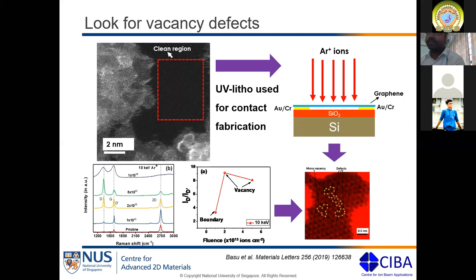So now what we can do in SIBA, as I told, we do ion beam related research as well. The idea is to create openings in graphene, right? We can use a broad beam exposure to expose graphene, because the ion beam, particularly a low energy ion beam, can create vacancy defects. Then you can see some defects created in the graphene. In general, the prediction is that graphene openings have to be less than 2 nanometers to be used for water desalination, which I'll come to later in my talk. With this kind of exposure to the ion beam, you can create monovacancy defects in the graphene lattice. You can probably see the contrast, right?